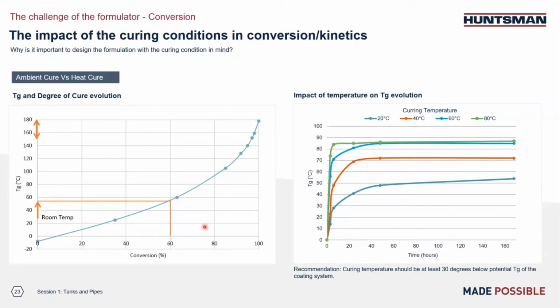And so usually we would recommend the curing temperature should be at least 30 degrees below the potential TG, right? So for this high TG system, if we really want to push to a higher conversion rate, you might want to cure at at least 150 degrees C to obtain the highest TG. On the right side, we have another system showing that the curing temperature makes a big difference.